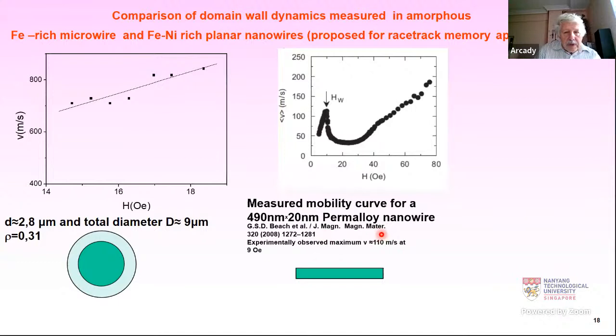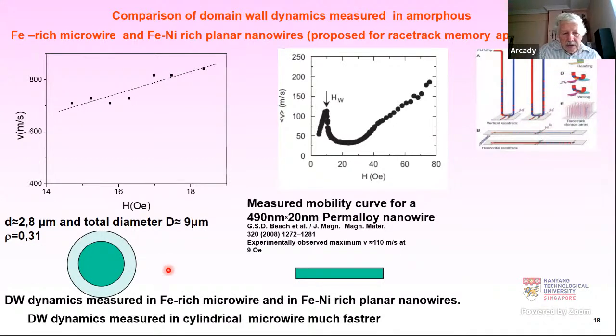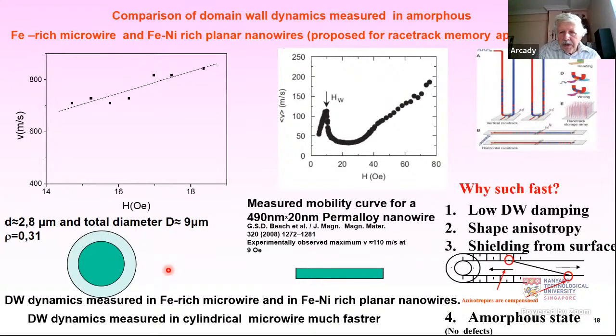And there are different viewpoints on the origin of such faster domain wall propagation. One, of course, is related to the perfectly cylindrical shape of our samples, and this is, in fact, quite relevant for the application. Another one could be related to low domain wall damping, probably related to the amorphous structure of our sample, and also shielding from the surface, because one of the important origins of the pinning of the domain wall is related to the surface roughness of the sample.